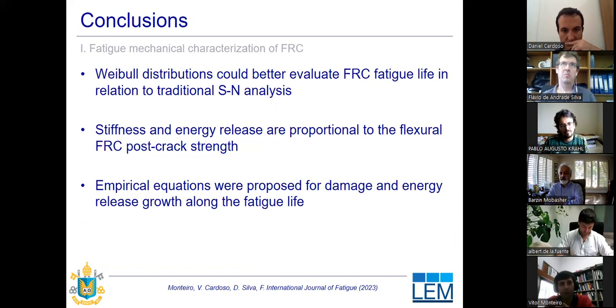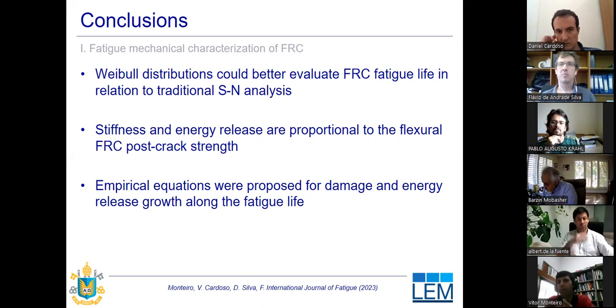So some of the main conclusions of this first section were that the Weibull distributions are a good methodology to evaluate the fatigue life of FRC using probabilistic methods, a more powerful methodology than using only the traditional mean fatigue life analysis. It was possible to propose and verify the stiffness decay along the fatigue life and verify the influence of the amount of fibers on the stiffness along the cycles. And finally, we also proposed some empirical equations to verify this degradation.